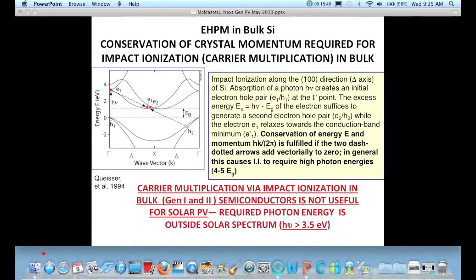But this process in bulk requires that not only do you conserve energy, you have to conserve momentum. And to conserve momentum, you can show, and it was shown very early, that it requires a very high energy photon, which has an energy that's outside the solar spectrum. Typically, it's 4 to 5 times the band gap of the semiconductor. So for silicon, the photon energy required to generate multiple electrons per photon is above 3.5 eV, which is outside the solar spectrum. So it's useless for solar energy conversion because those photons don't exist in the solar spectrum.